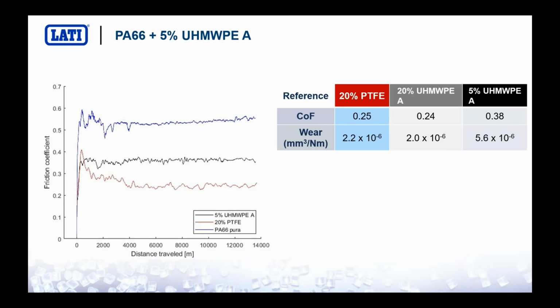We tried to halve again up to 5%, and as you can see, for sure, we faced a value of friction coefficient which was higher than the first two trials. And also the same for the wear factor. But okay, for sure, also with 5% of this kind of polyethylene, we obtain an improvement compared to the polyamide 66 unfilled.